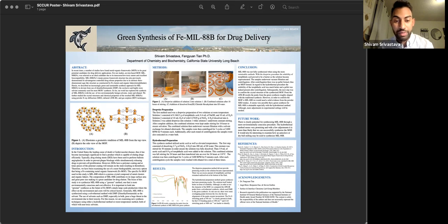We also used a hydrothermal preparation method that used elevated temperatures and water as a solvent. We dissolved 2.6 or 2.7 grams of iron chloride hexahydrate into water. And then once it was fully dissolved, we combined it with acetic acid and terephthalic acid. After the combination, we put it under stirring for about 24 hours, and then we baked it in the oven at 110 degrees Celsius. After 3 cycles of centrifugation, we were provided with better results, and we were able to have a pellet formed after centrifugation.